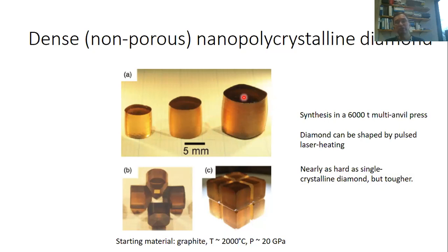And these nitrogen impurities are easily introduced either because there's a little bit of nitrogen in your carbon, or you just include a little bit of air in your capsule, and then that air, which is primarily nitrogen, becomes reactive with the carbon material, and you dope the diamond with nitrogen to some extent, which gives the diamond this yellowish brownish color.